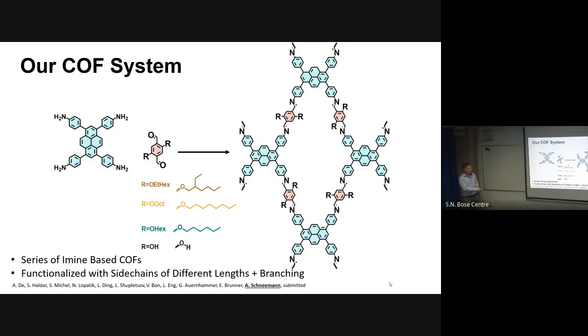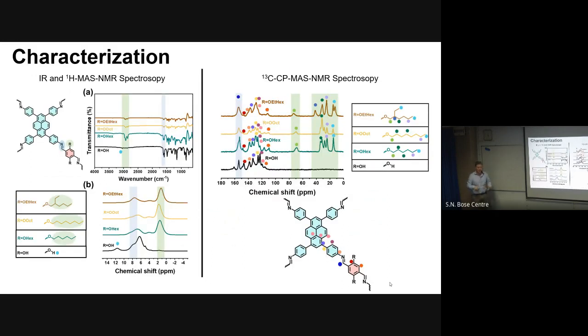We have a hexyl side chain, and just for the sake of pairing it, we have a material with no side chain. So we have a series of 4 imine-based COFs that we looked at. First of all, we did all the standard characterizations to know that the material is actually what we wanted it to be. We can see from the IR spectra that we have indeed the side chains installed. Here we have our CH vibrations. Then we also can see that we found the imine bridge, and that none of the starting materials is left.